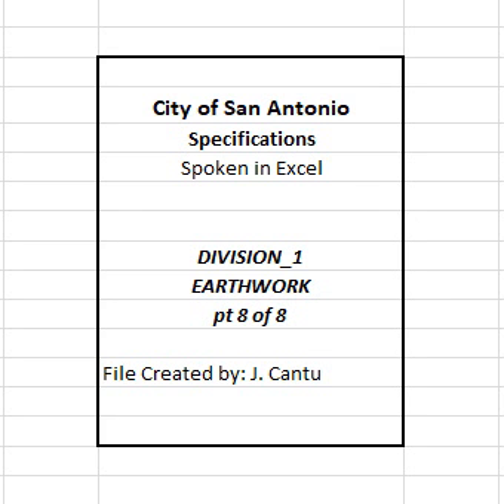Remove material that does not meet density requirements. Remove areas that lose required stability, compaction, or finish. Replace with cement-treated mixture and compact and test in accordance with density control methods. The engineer may accept the section if no more than one of the 5 most recent density tests is below the specified density and the failing test is no more than 3 pounds per cubic foot below the specified density.